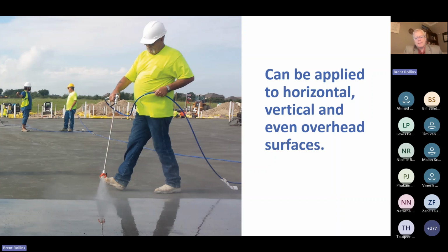Now, that application process, just to give you an idea of what it looks like, the spray is happening. You're applying very much like a traditional spray applied curing compound or sealer, but it does only take one pass. With a 50% overlap, you apply a quantity to an area. So you'd have X number of liters per square meter, for instance, and it enters the concrete where it reacts, closes that void structure with a reaction product that is common to concrete, CSH, calcium silicate hydrate, the same reaction product that gives concrete strength and durability. So this is the beauty of colloidal silica: you're essentially filling void structures with more concrete. It's a permanent change to the microstructure. It can't be removed, and it's deep. So the only way to get rid of it is to remove the concrete itself.